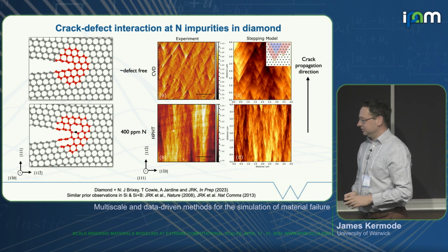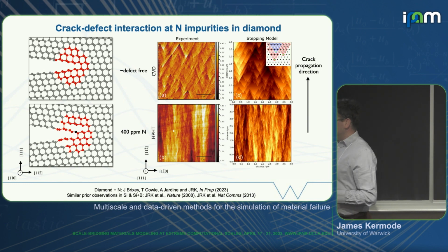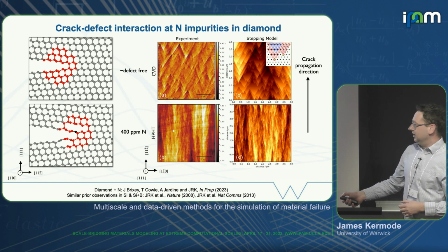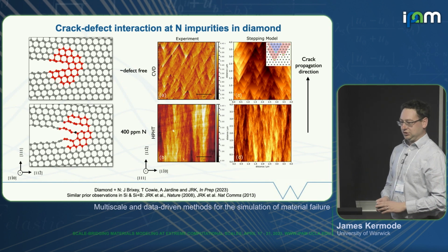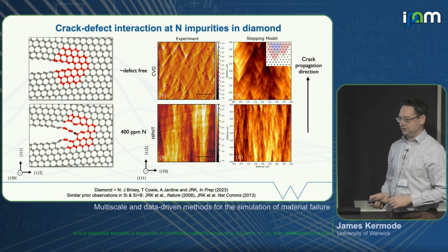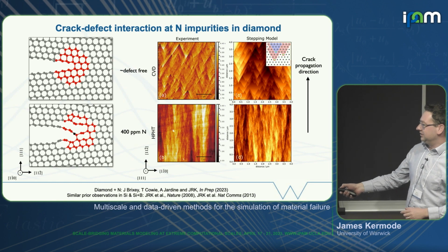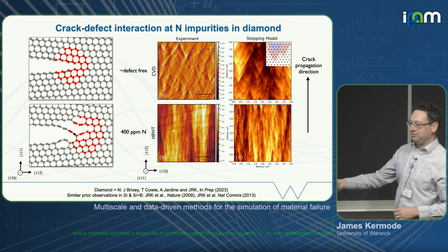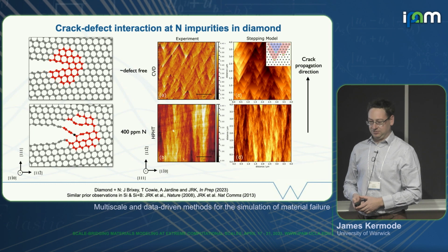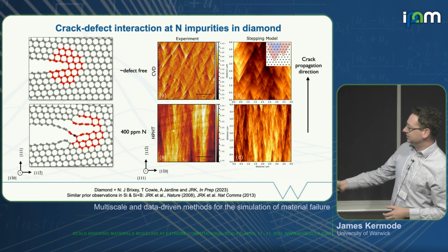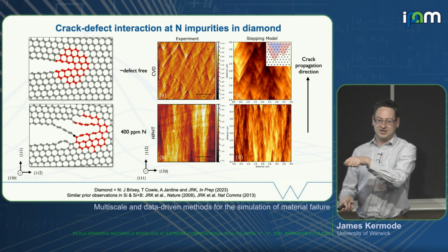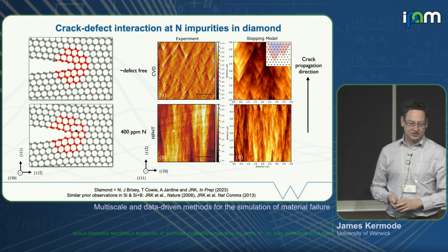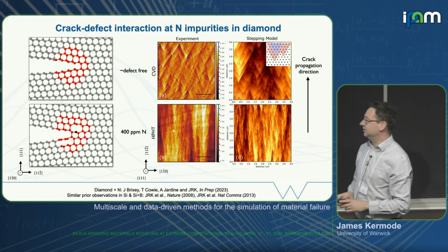and we get images in reasonably good agreement with the experimental observations. But a big challenge here is that these are very expensive calculations and that we can only do short duration simulations. So it would be better to try to incorporate information from the density functional theory calculations into improved atomistic models so that we don't have to keep calling it. Especially when you look at a simulation like this, you can see it's doing the same thing again and again. So it's a little bit wasteful to keep calling quantum mechanics.